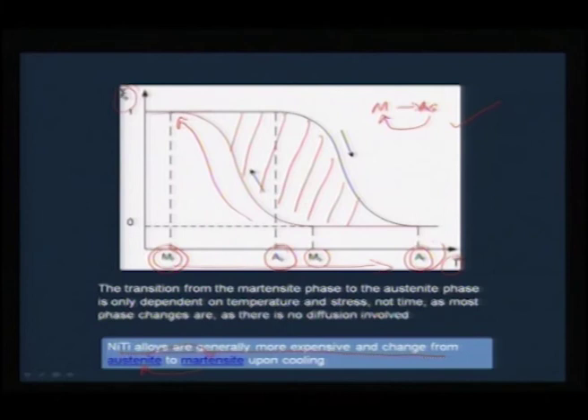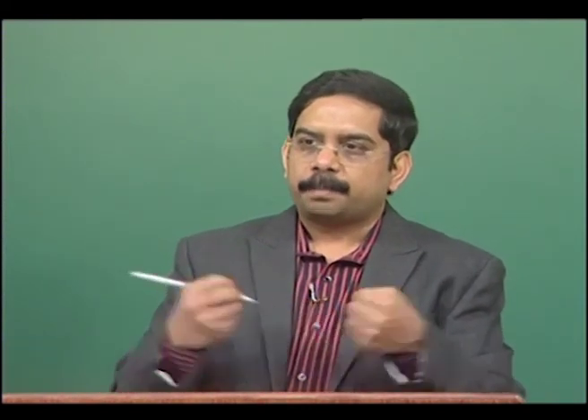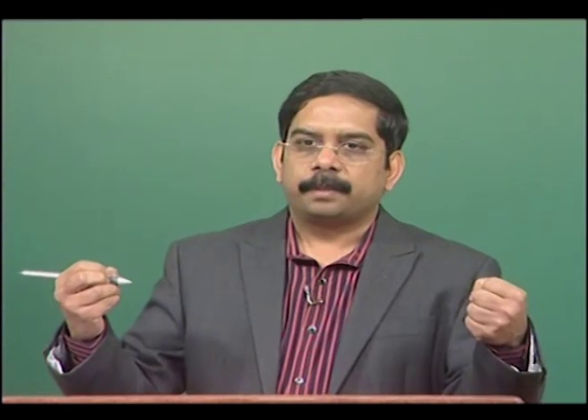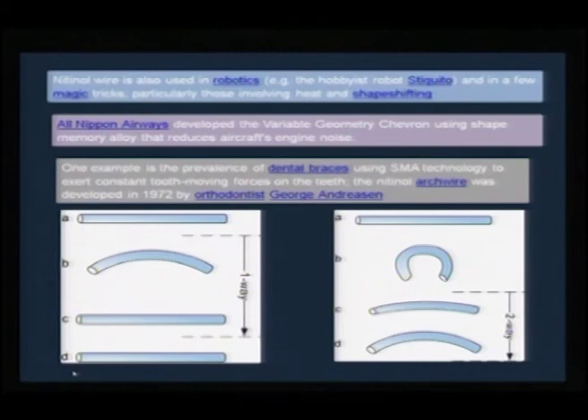So this is very important, and these alloys can also go through this martensite to austenite transformation, not necessarily with respect to temperature, but also with respect to stress, that is pressure. So you can also apply just pressure without temperature, at a particular isothermal condition, and bring about this phase transformation. Okay. So nitinol wire in terms of application is used in robotics because of the shape memory property. You can actually design robotic instruments using nitinol wire, that is why it is very costly, because you can use it for many functional applications.